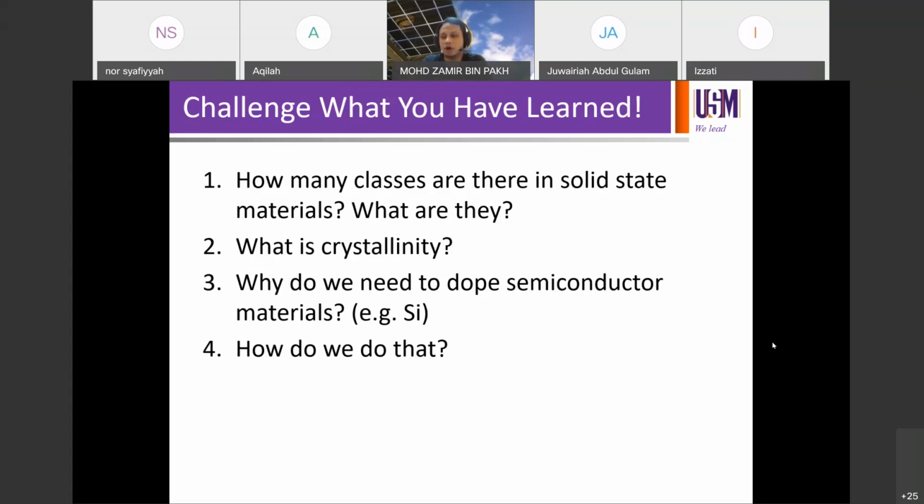Give me some examples of dopants from group 3, or group 13. Boron, yeah, boron is a common one. You may also use gallium, for example. In the solar cell industry, they used to use boron-doped silicon for p-type wafers to fabricate solar cells, and now they're slowly moving into gallium doping, because it's more stable in terms of solar panel performance in the field. When panels are in the field, they are subjected to fluctuations of temperature, heat, moisture and other parameters. They found that gallium-doped silicon is more stable than boron-doped silicon.